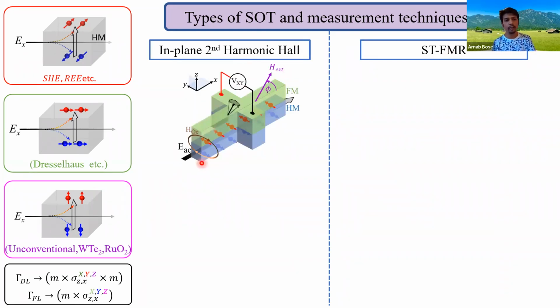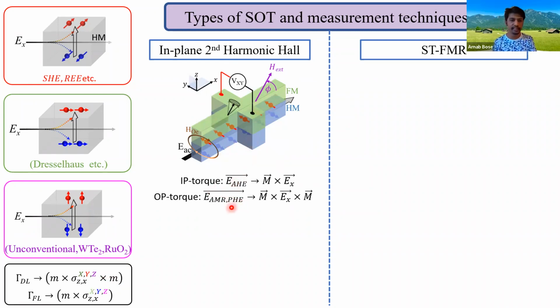In the second harmonic Hall, we run low frequency AC current in the ferromagnet heavy metal bilayer. We measure the DC voltage, we measure the second harmonic Hall voltage by a standard lock-in measurement technique, while we rotate the magnetic field in the plane. Due to various current-induced torques, the magnet oscillates in the plane and out of the plane. It oscillates in the plane due to out-of-plane torques, and it oscillates out of plane due to the in-plane torques. And when it oscillates, its resistance also oscillates due to anomalous Hall effect and planar Hall effect.